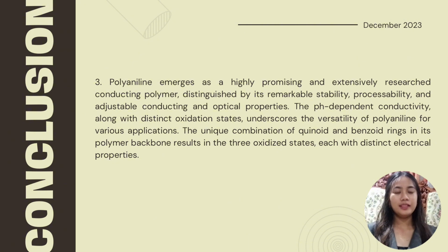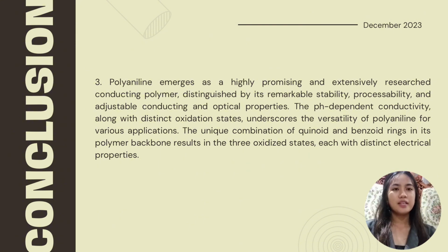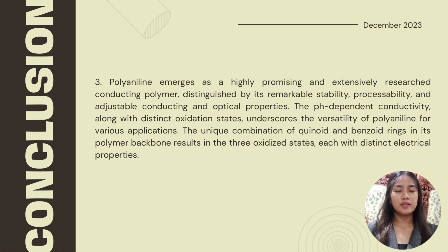For the conclusion on flexibility, polyaniline emerges as a highly promising and extensively researched conducting polymer, distinguished by its remarkable stability, processability, and adjustable conducting and optical properties. The pH-dependent conductivity, along with distinct oxidation states, underscores the versatility of polyaniline for various applications. The unique combination of quinoid and benzoid rings in its polymer backbone results in three oxidation states, each with distinct electrical properties. Notably, the flexibility of polyaniline, attributed to its reversible redox reactions, sets it apart from other conductive polymers like polypyrrole.